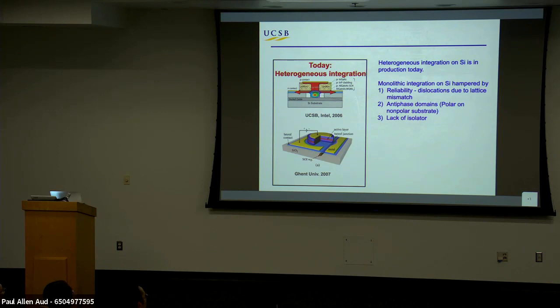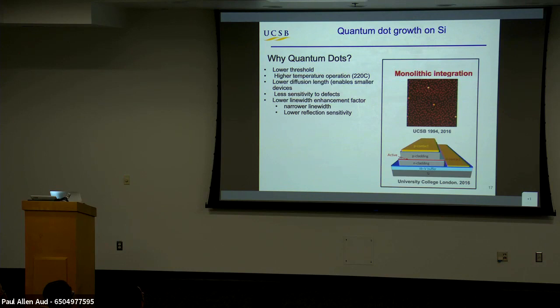The problem when you grow is that there's dislocations, there's lattice mismatch. And because of dislocations, there's a real reliability problem here, dark line defect growth. There's antiphase domains. You're growing a polar gallium arsenide indium phosphide material on a non-polar silicon surface. And then again, the lack of an isolator is an issue. And so quantum dots, I think, solve all of those issues.